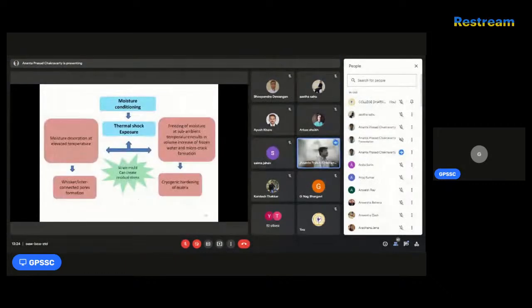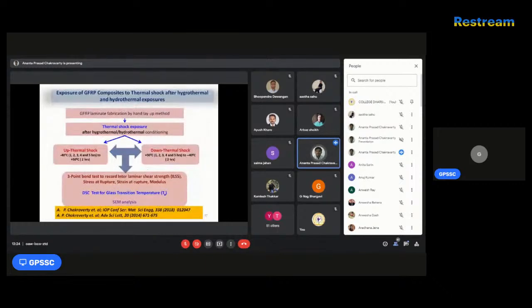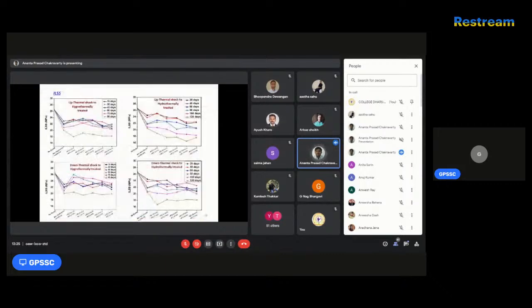So generally after moisture conditioning, when the material is put into an environment where the temperature changes from lower to higher or higher to lower, there will be moisture desorption or moisture absorption. And when it goes from higher to lower, the moisture can be frozen and there will be swelling and material integrity will be lost. So with respect to the combined behavior of this moisture desorption and the cryogenic hardening, there will be strain misfit. You can also go for this work that has been conducted, where the material is fabricated and exposed to different thermal shock environments from low temperature to high temperature for different durations, and their properties are studied.